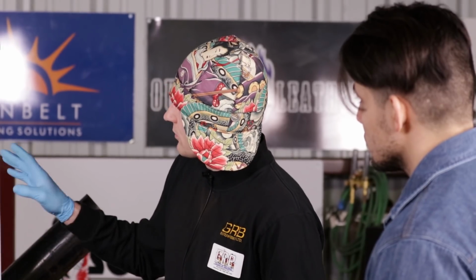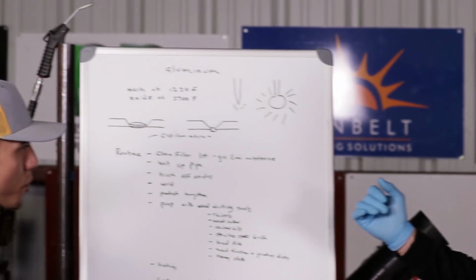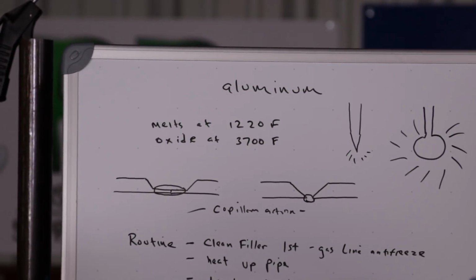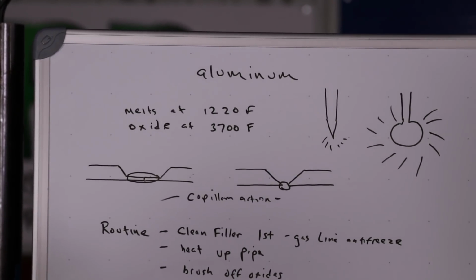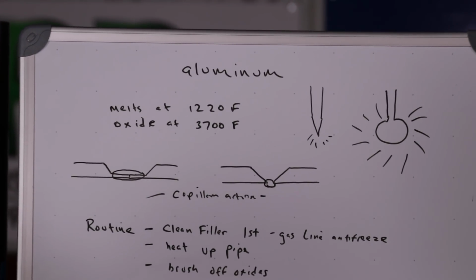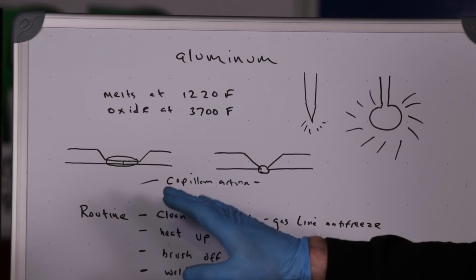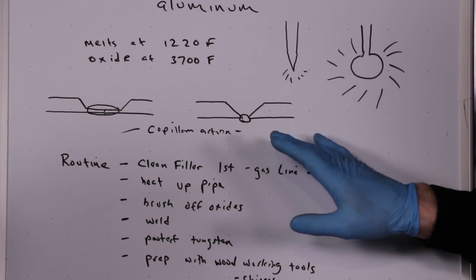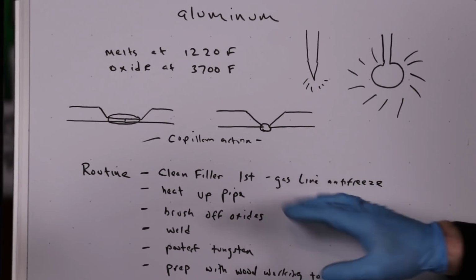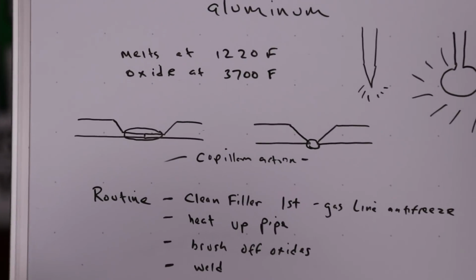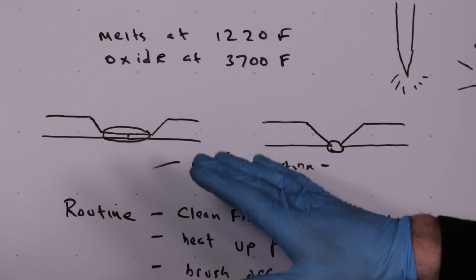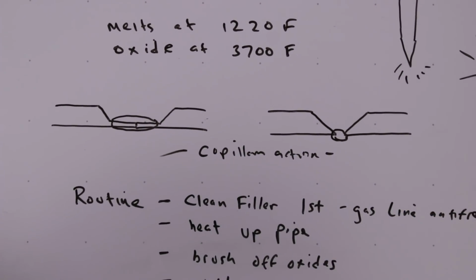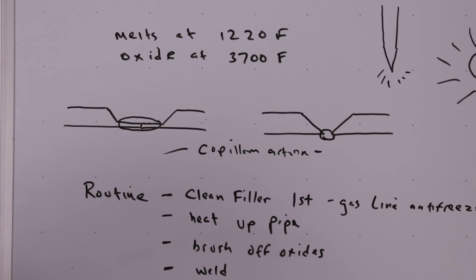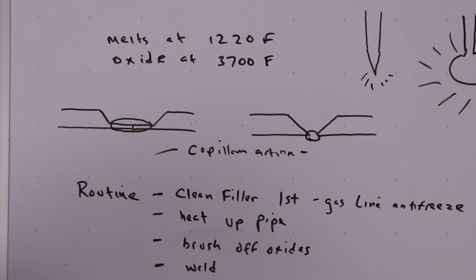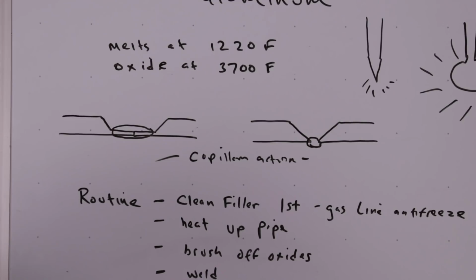But basically when it comes to aluminum, there are two different fit-ups that I've been taught and shown at the trade facility there. There's the extended land fit-up, and there's an open root butt joint. With the extended land fit-up, you have a 3/32 land and a 3/32 extended land. They'll be butted up tight, and you don't have to use a backing purge unless it's for critical applications, but you can slam it up tight.